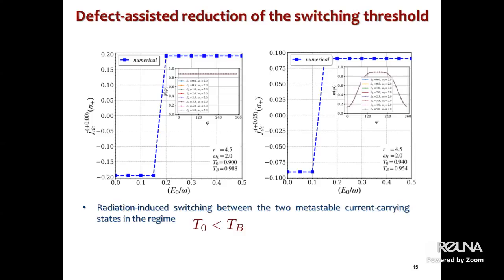So the left figure displays the switching effect for a clean sample, the right one for a ring with a defect. The switching occurs in the clean ring sample approximately for amplitude 0.2, and for the right panel for 0.15. So we see that the defect reduces the switching threshold by approximately 25%.